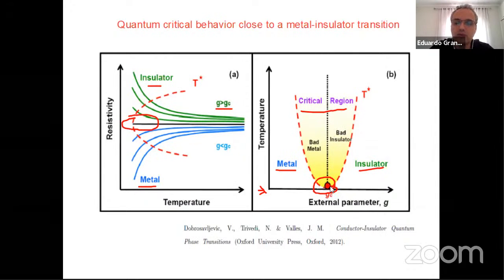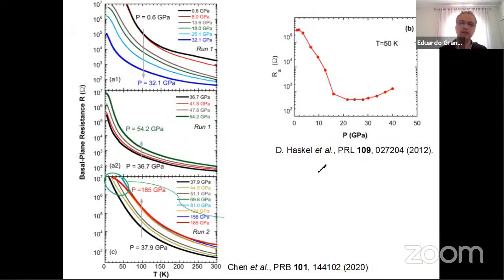So when you have a quantum phase transition, even though the quantum phase transition happens at 0 temperature, when you have the external parameter exactly at this transition, there is a very strange behavior that happens even at high temperatures, and that's why we're interested in these kinds of materials.